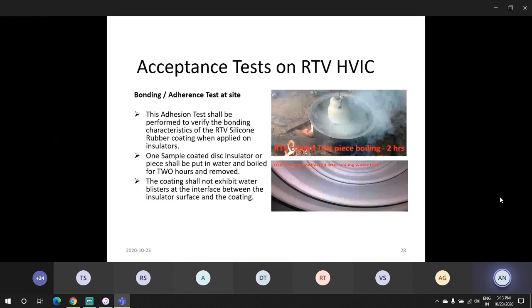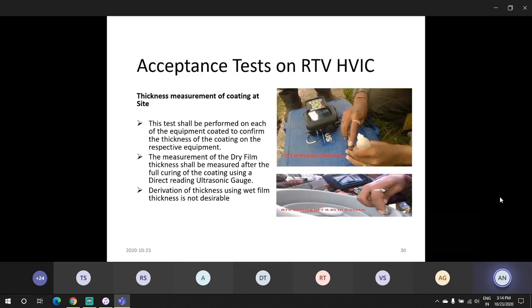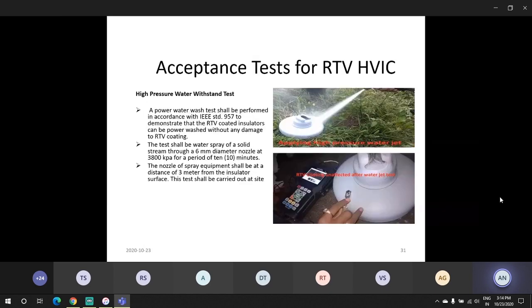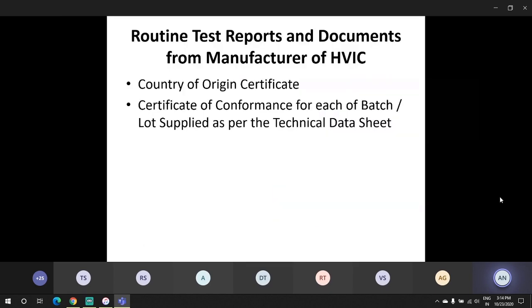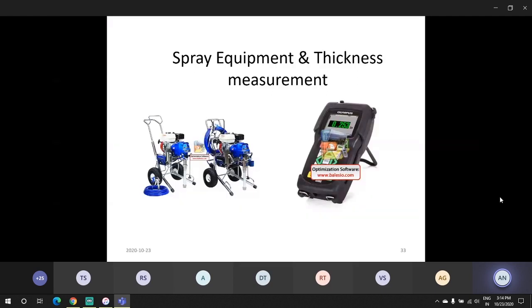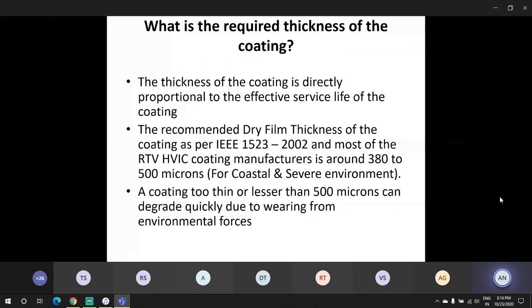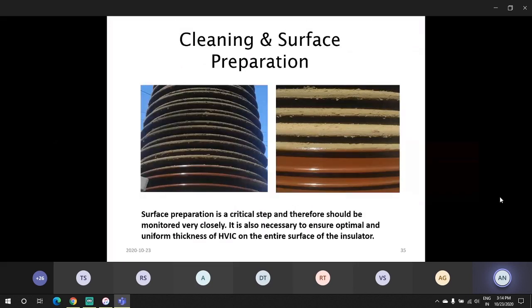These are certain acceptance tests which are mandated in the utility specifications like Power Grid: boiling water test, hydrophobicity test, thickness measurement, high pressure water withstand test. This is the spray equipment and the thickness measurement gauge which is used by us for ensuring the thickness specified by the end user. This is the surface preparation. We have to ensure a clean surface preparation, as good as a new insulator, before the coating is applied.